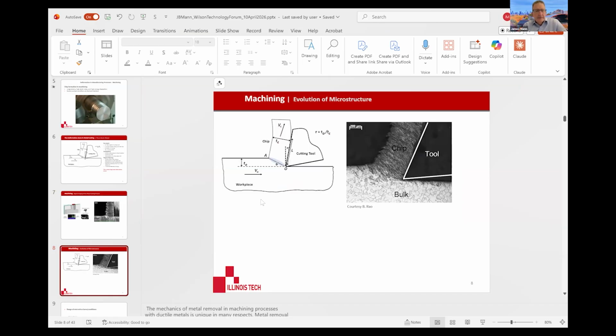So for those of you that are material scientists, you can appreciate that the typical metals and alloys have some bulk microstructure. It's often micro scale in terms of the size of the grains, micron scale. But the chip itself, and this is on the right-hand side, this is just a conventional metallography, in this case of titanium being cut. And you can see that from an optical microscopy perspective, there is really nothing you can observe in the chip. And that's because the actual grain structure of the chip is now refined below the resolution of optical microscopy.